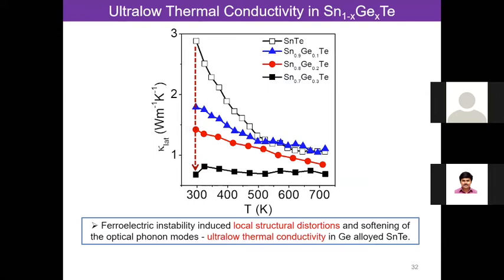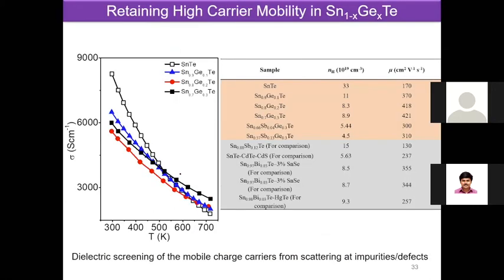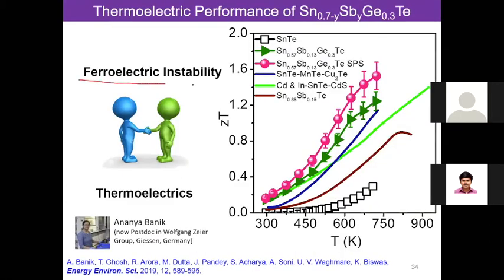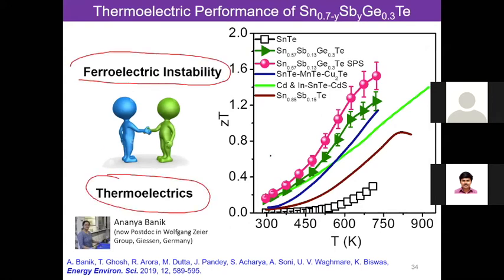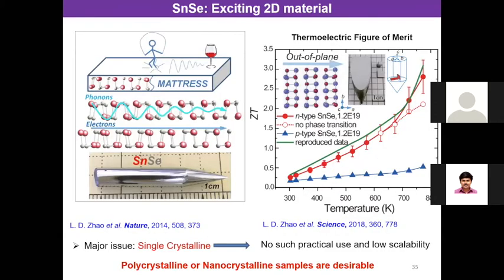And this is really an intrinsic factor because we don't have nanostructuring or mesostructuring or microstructuring in this material. And that comes from basically combining these two fields, ferroelectric instability and thermoelectrics. First time we have combined them and we get a really high ZT in this material, around 1.6 in a lead-free system. So now with that, I'll complete in another 4-5 minutes, saying a few more examples.